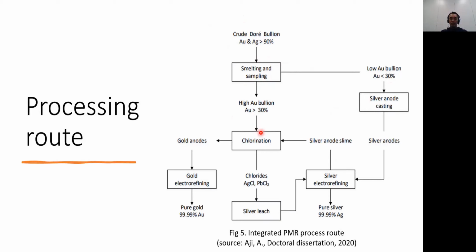And then the high gold bullion will go to chlorination. As I mentioned again, this is a practice in Rand refinery. Not all precious metal refineries have this kind of facility. After chlorination, they will produce gold anodes. So the other materials except gold, all the impurities, will form chlorides, which will precipitate, and then go to silver leach. So the silver chloride in this material is reduced into silver metal, and then it will go to silver electrorefining. But the gold will go directly to gold electrorefining to produce 99.99% gold. Yeah, I took this from my doctoral dissertation.